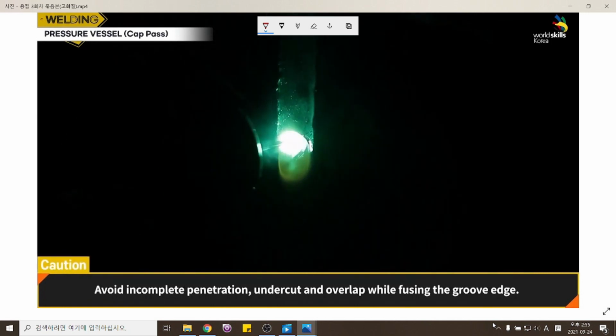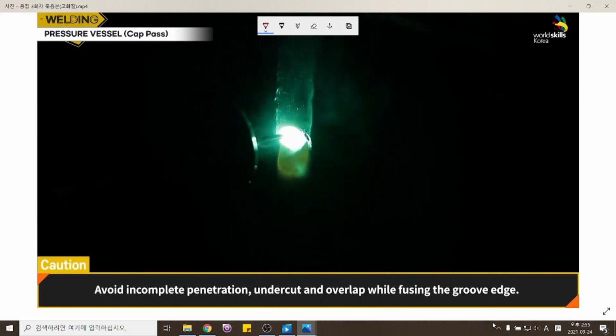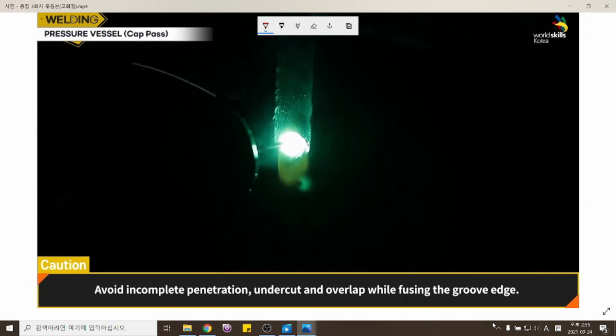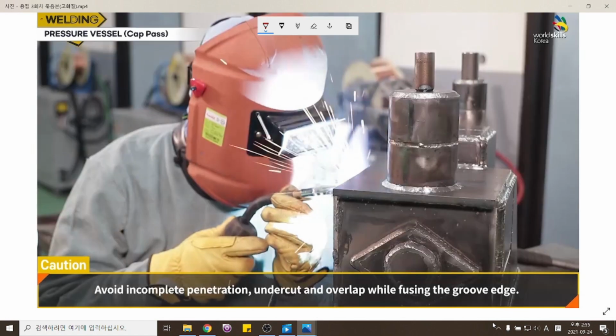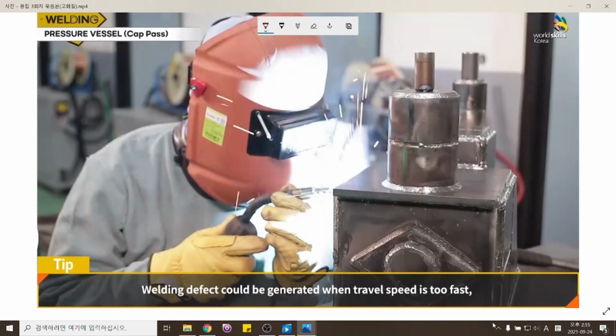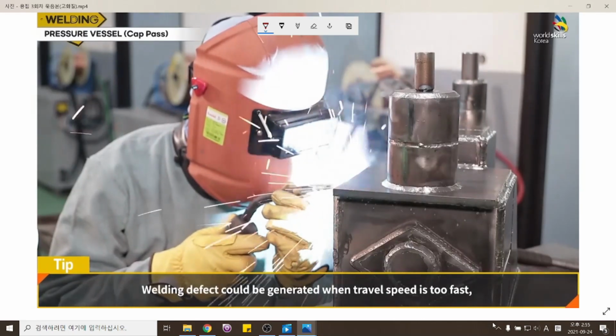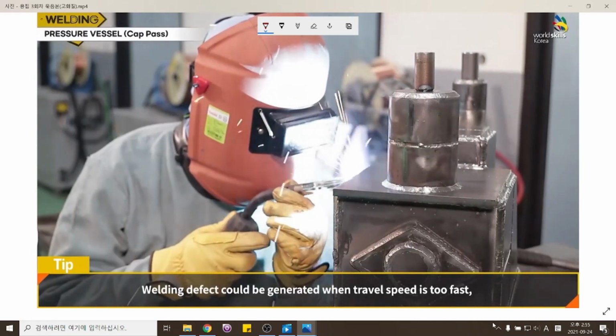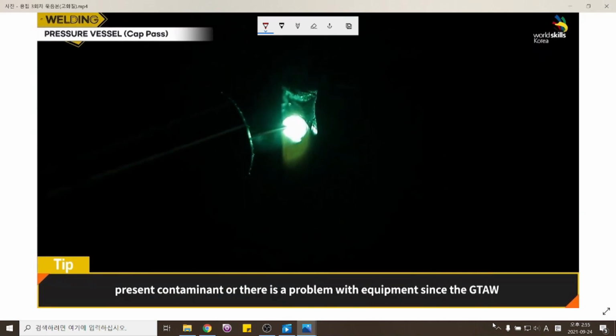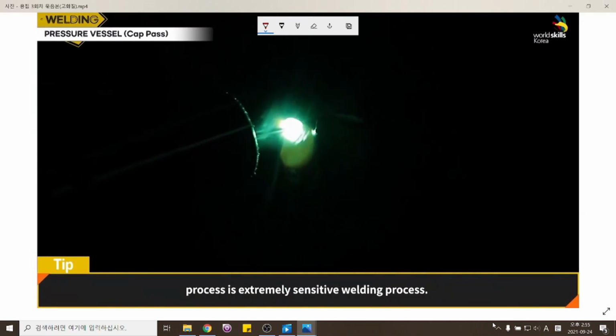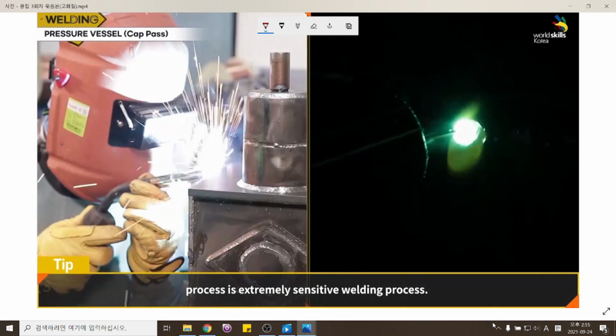Avoid incomplete penetration, undercut, and overlap while fusing the groove edge. Welding defect could be generated when travel speed is too fast, present contaminant, or there is a problem with equipment since the GTAW process is extremely sensitive welding process.